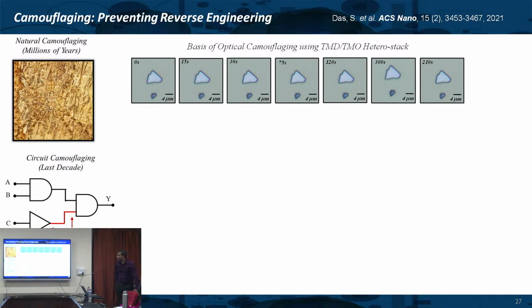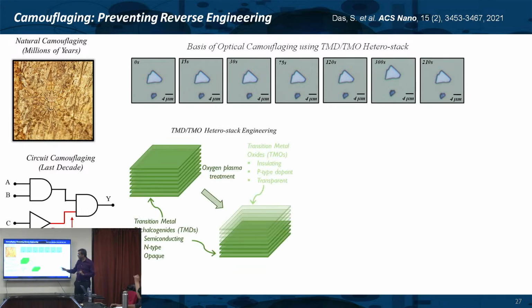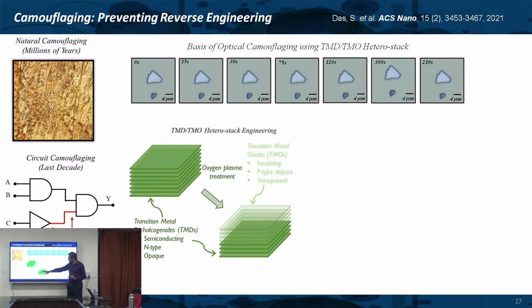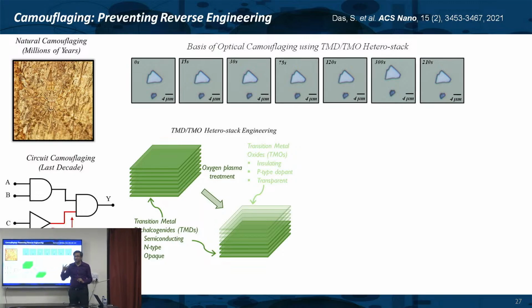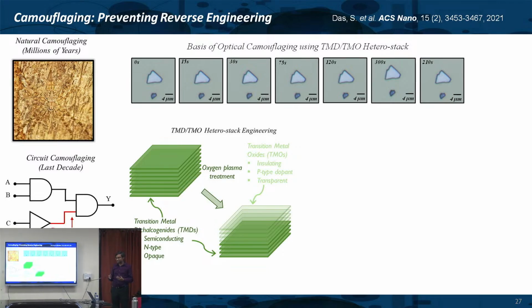That is possible with the 2D material because of this. If you have not a monolayer flake, but a multi-layer flake, then this material is primarily N-type. Most of the 2D materials are N-type. Then we spoke about this oxygen plasma treatment, didn't we, right? When you treat it with oxygen plasma, it's a self-limiting process, but you can actually convert the top layer into transition metal oxide, like moly oxide, tungsten oxide. And these oxides are transparent, because most of the oxides are transparent. So therefore, the appearance of the flake does not change.